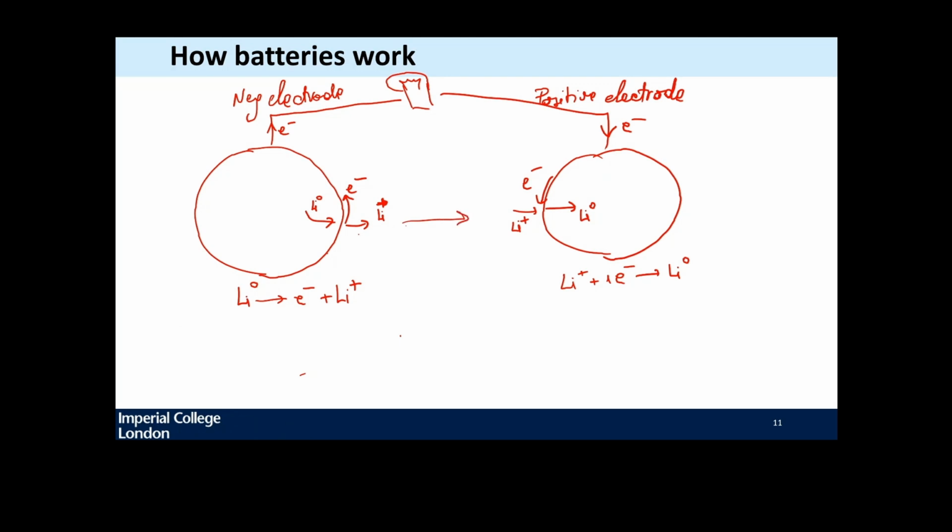inside the electrolyte. And I need here to have an available location or interface for this reaction to happen in the reverse direction, for lithium plus and one electron coming from the outside to provide a lithium 0 that is now inside the electrode. And there has to be space here, which means the lithium 0 has to be able to diffuse into the electrode.